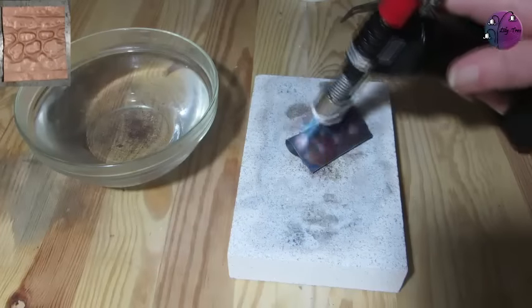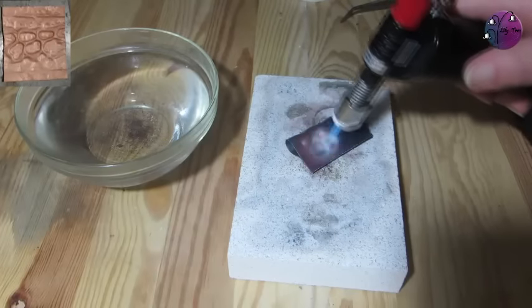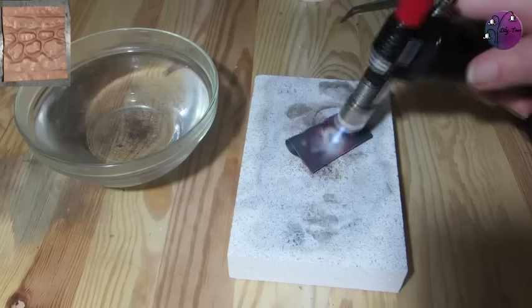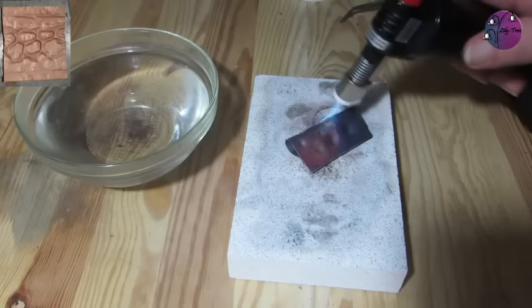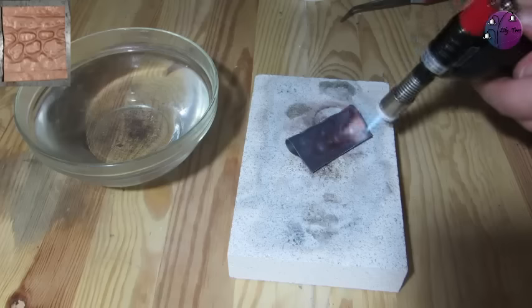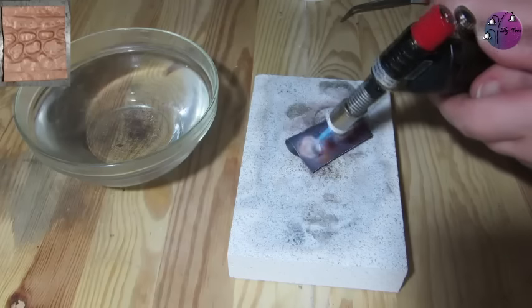So I'm just going to heat the piece of copper with the torch until it reaches a glowing pink color. Then I know it's annealed and it will be soft enough to continue hammering.